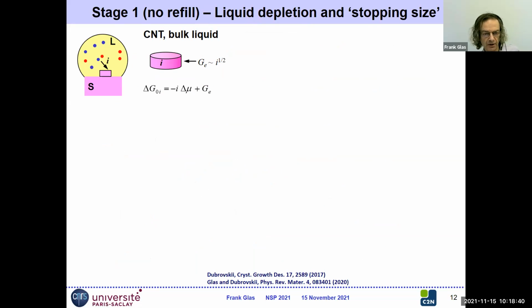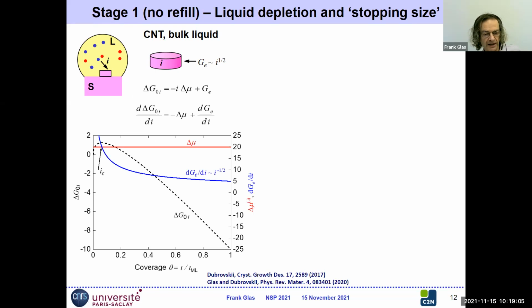So let us look at the stage 1 without refill. So today I will assume that it's instantaneous. So again, I plot here on the left the reference condition for bulk phases. So we have the work of formation, the decrease of free energy of the system when I form a nucleus with i pairs from the liquid. So that's exactly what I said before. And if we plot these quantities, we remember that the critical size corresponds to the equality of the derivatives of these two terms with respect to size. So it's exactly when delta mu, the chemical potential, which in both systems will be assumed to be constant, equals the derivative of the energy of the edge of the island that I create with respect to size. So here I plot these two terms.